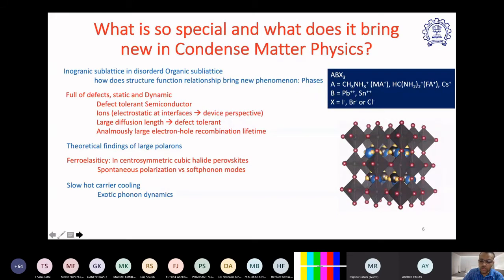Hot carrier solar cells allow you to get a VOC more than the band gap of the semiconductor, because if you can pull out the charges at higher energy than the band gap of the material, then your quasi Fermi level splitting will basically beat the limit, and you might get a VOC which will be higher than the band gap of the semiconductor.